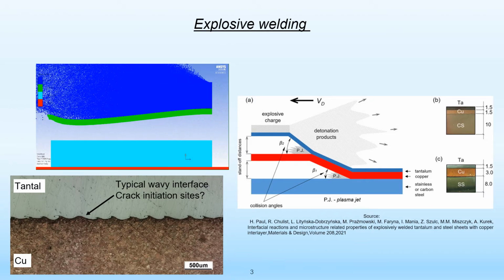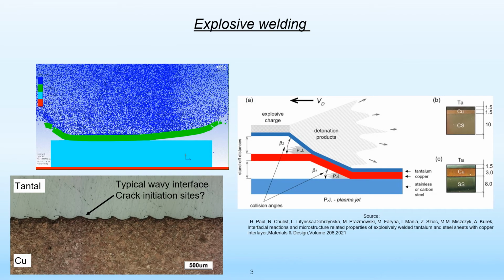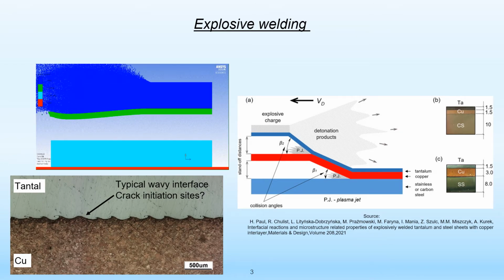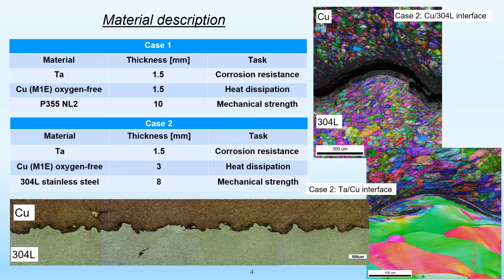The bond produced during explosion welding has a characteristic wavy form. Can it be a location of fatigue cracks? Let's see. Two metal composites are the subject of this study. In both cases, 1.5 mm thick tantalum layer was used for plating. In case 1, 1.5 mm thick oxygen-free copper layer was put between flyer plate and a P355 NL2 steel plate. In case 2, on the other hand, the thickness of the copper layer was 3 mm, and the material used for a base plate was 304L stainless steel.